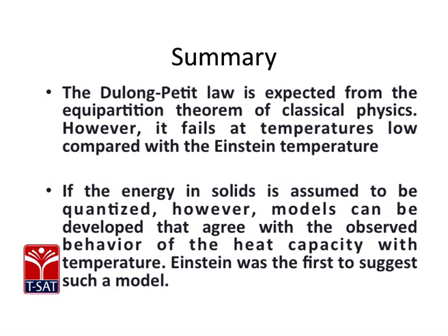So, in summary, the Dulong and Petit law is expected from the equipartition of energy theorem of classical physics. However, it fails at temperatures low compared with the Einstein temperature. If the energy in solids is assumed to be quantized, however, models can be developed that agree with the observed behavior of the heat capacity with temperature. Einstein was the first to suggest such a quantum mechanical model, whereas Debye's model is a more successful model in showing all the types of vibrations.